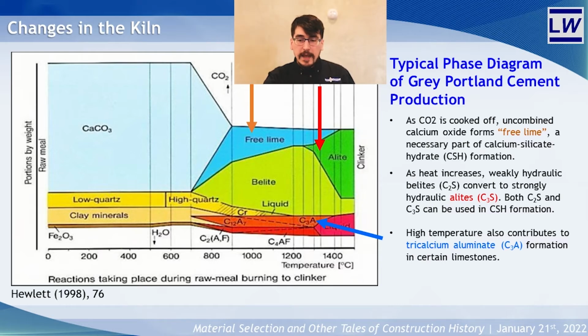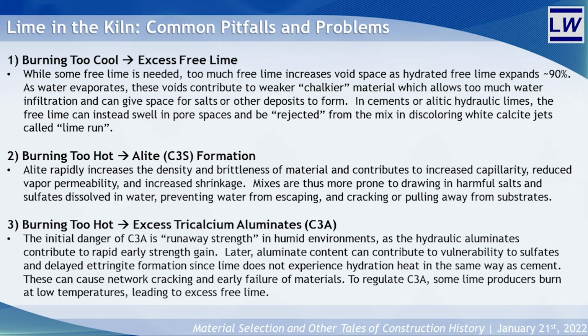However, because both natural and added alumina can be used to make a hydraulic lime, it's not always controlled for in the same way in lime production. While free lime content is certainly desirable in limes of all types, there can be such a thing as too much free lime. If the kiln is not hot enough, or if there are not enough hydraulic clays naturally within the stone, not enough free lime will recombine into belite, resulting in a mortar product that is much too calcium oxide rich. When hydrated, calcium oxide expands about 90%, leaving relatively large, frequent voids in the cured product.